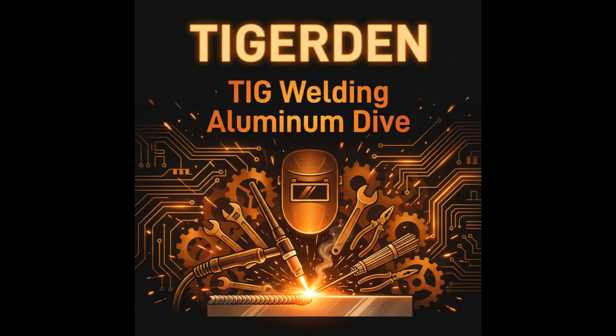Let's get technical for a second. AC balance, frequency. These are the pro settings that confuse everyone. Give us the Tigerden explanation. Think of AC balance as your cleanup versus penetration knob. If you've got it set to more electrode positive, you're doing a ton of cleaning, blasting that oxide off, but you're putting a lot of heat into the tungsten. If you go more electrode negative, you're drilling deep into the metal, but the weld might look a bit sooty because you aren't stripping the oxide. I usually find a sweet spot around 70% to 75% DC negative.